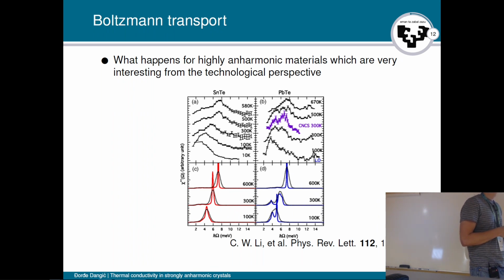However, there are some materials whose lattice thermal conductivity we do care about, and those are, as I said, thermoelectric materials. One of the most famous ones is lead telluride. It has a very high thermoelectric figure of merit. And if we do a similar type of experiment for lead telluride, we see these satellite peaks appearing in the signal, which is evidence of a highly anharmonic material.